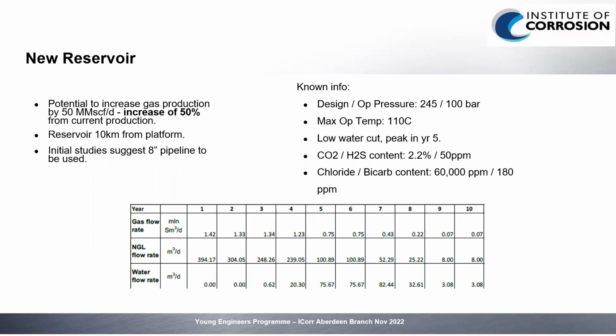Like I say, the reservoir is 10 kilometers away, and studies have suggested that an 8-inch pipeline is going to be the best way to deal with this. I've got up on the right-hand side there the known info: design and operating pressure, temperature. We've got CO2 and H2S, so this is a sour reservoir. And then we have our chloride and our bicarb content as well. At the bottom, we've got the production profile for the 10-year period. The main takeaway there is that in the first 2 years, we have basically zero water cut. So we shouldn't have too many corrosion issues in the first couple of years, but this increases up to about year 7 for it to peak and then drops off again toward the end.